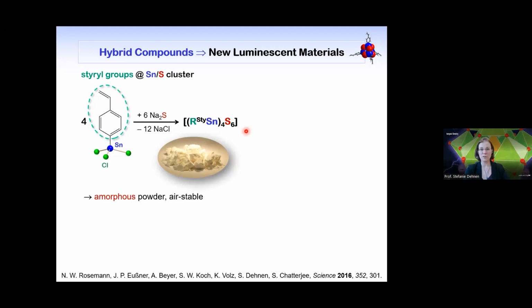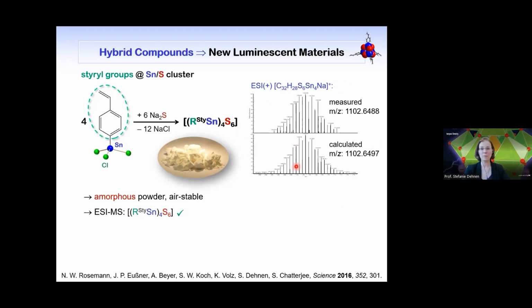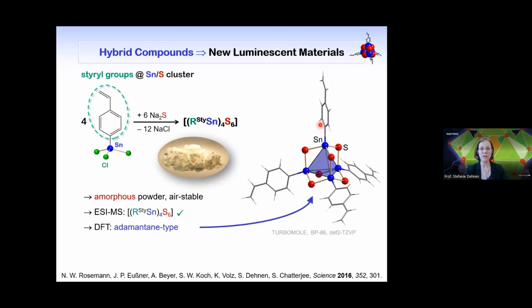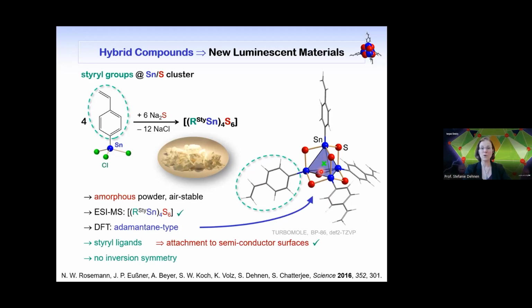So this reaction was on one hand successful because we got a pure product, but it was amorphous. We couldn't get the structure from it. An air-stable powder, completely amorphous. So we took a mass spectrometry and confirmed the composition. We calculated the structure and saw that this is an adamantane type basis here. So it's very much related to the inorganic salts I've talked about, but we have organic groups on this adamantane type cluster core. And these groups are styryl groups, so they can be attached to semiconductor surfaces. This worked out nicely. But then we recognized that there is no inversion center on this cluster.